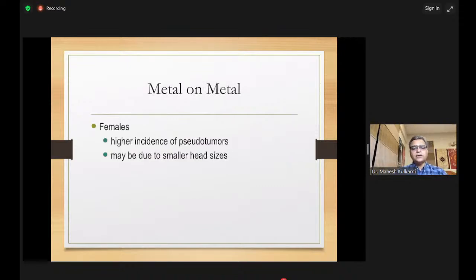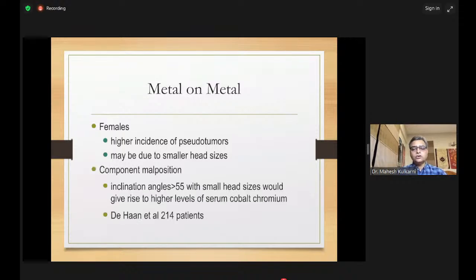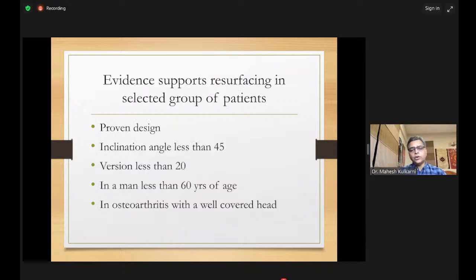We found out that there were higher incidence of pseudotumors, especially in females, maybe because of smaller head sizes, and if there were component malposition. So if you had edge loading with a vertical hip socket, I think you had more problems as compared to a closed cup. But there is still evidence which supports resurfacing in selected group of patients.